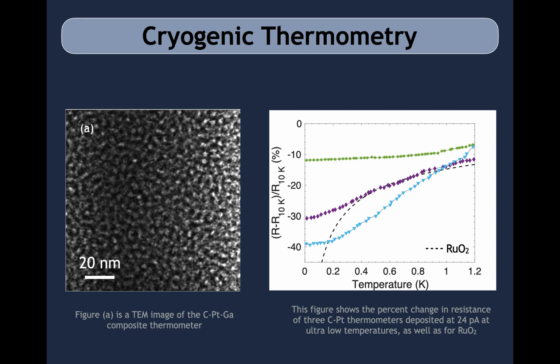However, the FIB-deposited carbon-platinum composite has unique conduction characteristics independent of either pure platinum or carbon that make it a sensitive thermometer at cryogenic temperatures, and it is extremely easy to pattern directly onto the sample. Since the composite is amorphous, the thermometer resistivity is extremely dependent upon the sample morphology. As you can see in the plot on the right, 3 thermometers deposited at the same ion beam current have slightly different percent changes in resistivity. While slightly variable, the sensitivity of these thermometers is still comparable to leading commercially available cryogenic thermometers, specifically ruthenium dioxide, which is also plotted.